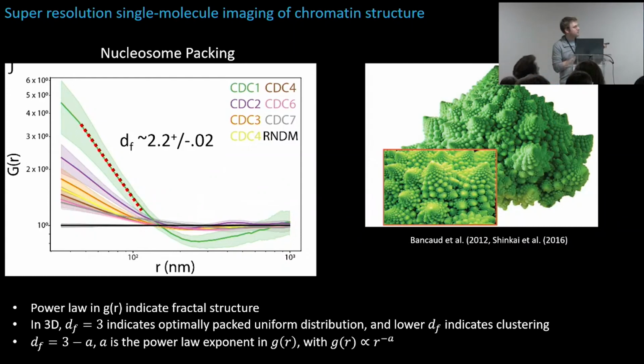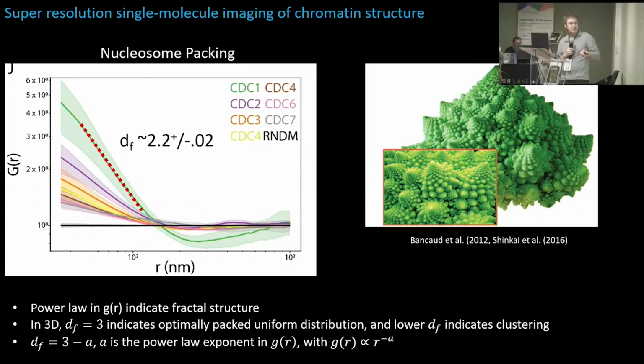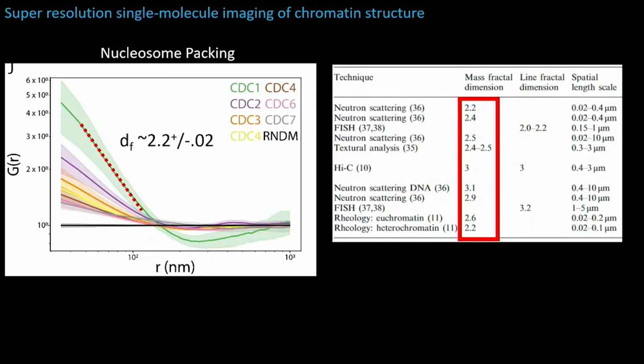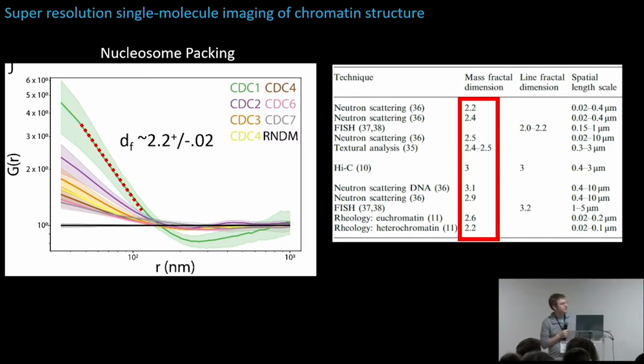basically the slope of this plot on a log-log scale, extract the fractal dimension from the dimension minus alpha, or minus a, which is the power law exponent, which is the slope of this line, and it tells us something about the spatial organization or spatial packing of nucleosomes in these different density chromatin regions. So if we look on average, I'll just pull one example here. This is not unique to us. This is using localization microscopy. We see a fractal dimension of about 2.2. This is actually in large agreement with the fractal dimension of chromatin measured with a variety of other imaging technologies.